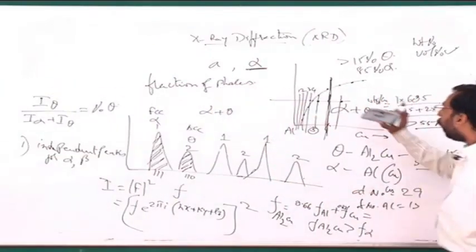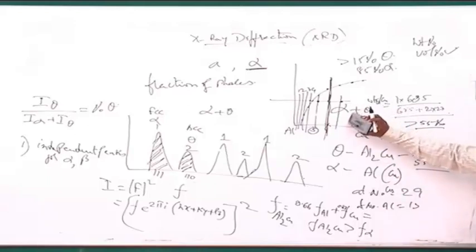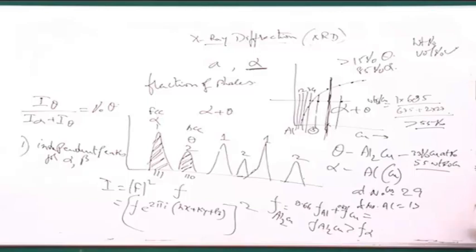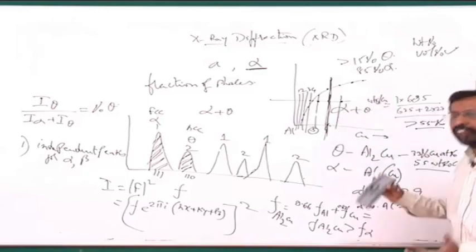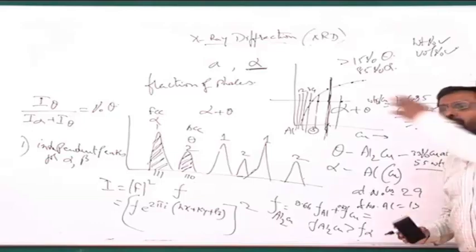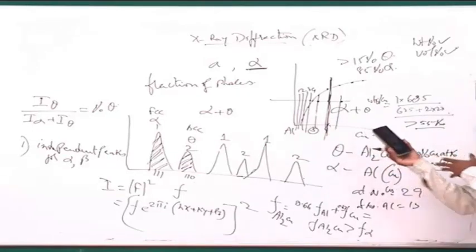And you look at the percentage that I am calculating from this phase diagram. From the phase diagram, if I am using the lever rule and finding out, what I am finding out is weight percent. I do not get volume percent there. And that's the usual problem that we face. How do I correlate my microstructure to my lever rule?